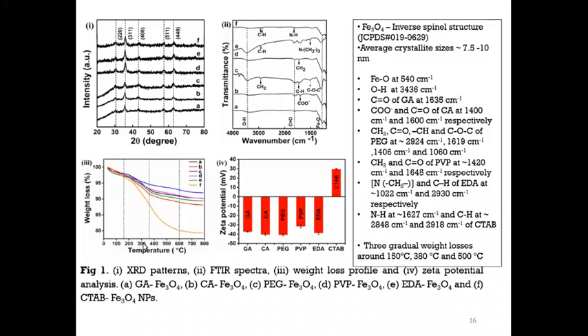Most of the organic molecules which we have used are burned around 350 degrees centigrade, and sometimes there is 5 to 10% weight loss, which is due to the surface functionalization of the nanomaterials. And the zeta potential, which is the electric double layer formed in colloidal suspensions because of the surface functionalization, we can get. With glutamic acid, citric acid, polyethylene glycol, polyvinyl pyrrolidone, ethylene diamine, we are getting negative zeta potentials because of the negative surface charge, but because of the N plus group in CTAB, we are getting a positive surface charge.